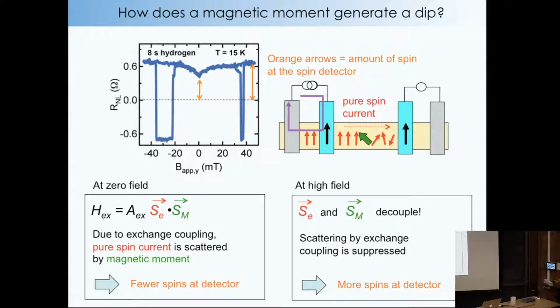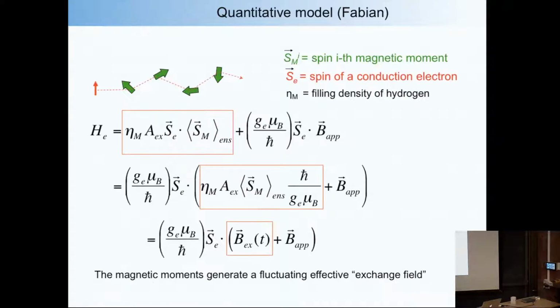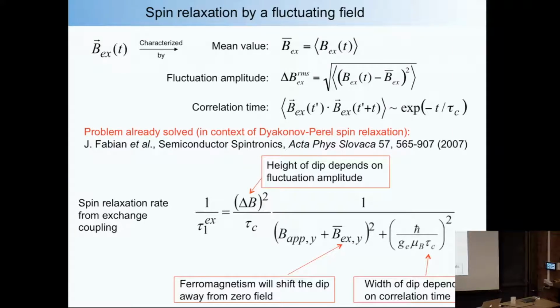So there's this idea of decoupling, which at low fields you'll have this scattering. At high fields, these will decouple. And the way to understand this, actually, Jaroslav Fabian had a model, and I just want to point it out. The idea is first you have an exchange coupling and an ensemble average of your magnetic moments. You can have this electron spin and it could hop from one defect to the other. And so what happens here is that you take this and you just do some algebra to it, and basically the exchange interaction looks like an exchange field that fluctuates, and it fluctuates because you're hopping from one to the next. And whenever you have a fluctuating magnetic field, Jaroslav had worked out the theory for this, and basically the fluctuating fields can generate spin depolarization. And here are the equations. I'm just showing you that they're there. I won't go into it too much.